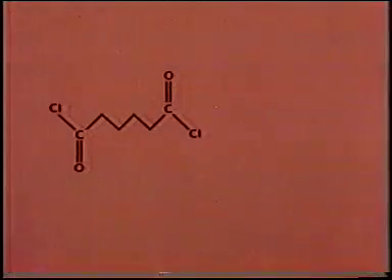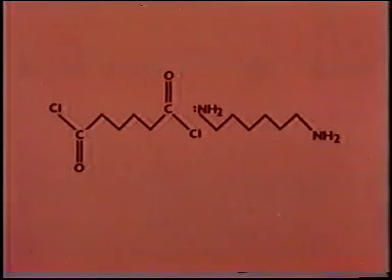You've seen an example of step growth polymerization in an earlier television program. Step growth usually goes by very simple chemical reactions, such as the formation of amide bonds. And the polymerization which we hope will be familiar to you is just one way of synthesizing nylon 6,6. Hexanedioyl dichloride reacts with hexane-1,6-diamine by attack of the nitrogen lone pairs on the carbon atom.